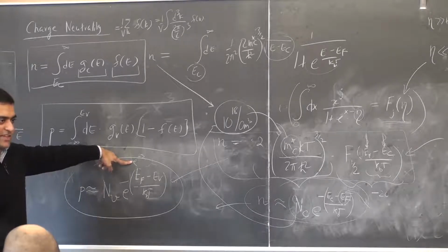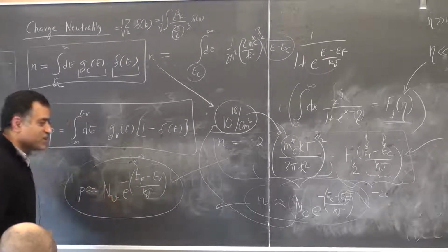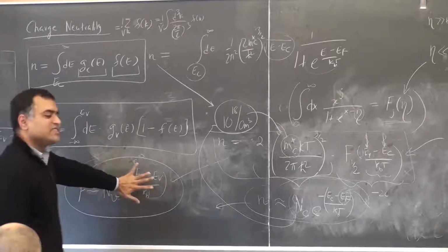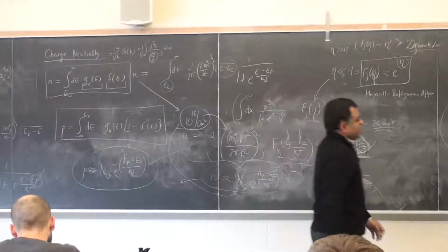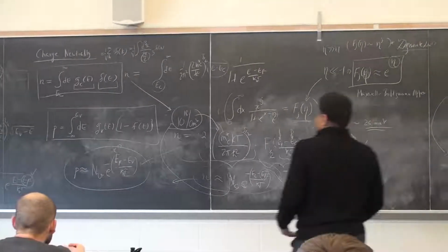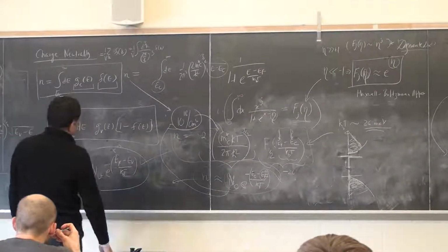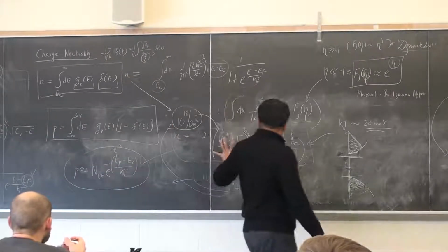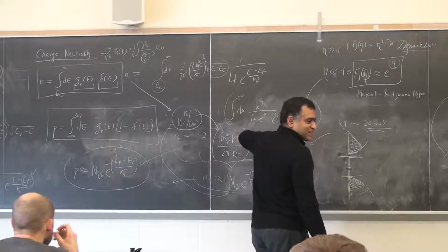It's roughly 20, so you get 1/20. So I know roughly how many electrons, and I don't have to go and do the math. I just know. That's why this approximation is used. It also gives you a clear picture that the carrier density should change exponentially. This is not as easily apparent in the buried integral here.